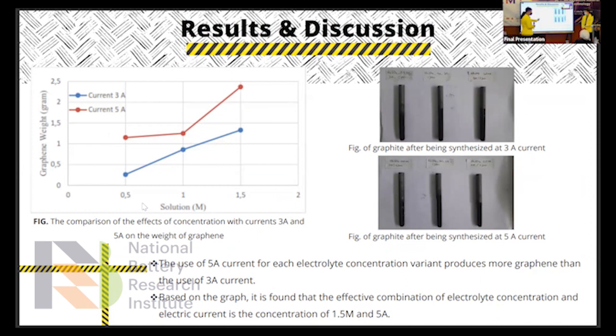So this picture shows the graphite after being synthesized, that we give to the sample. And from all these graphs and pictures, we conclude that the use of 5 ampere current for each electrolyte concentration variant produces more graphene than the use of 3 ampere current. And then, based on the graph, it is found that the most effective combination of electrolyte concentration and electric current is the concentration of 1.5 molar and 5 ampere.